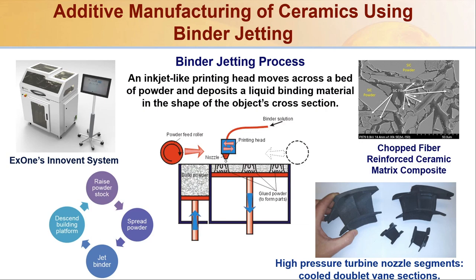bubble chart here. You basically have a powder stock, and then you spread the powder, and the binder jets it, and then the build platform descends, so you basically have the parts going down, and then this building platform is going up. We have done a number of complex shapes in the previous programs, and we have also looked at whether you can add small chopped fibers. Actually, these were fibers about 70-80 micron long. So you can see there are long fibers which can also be added in the powder